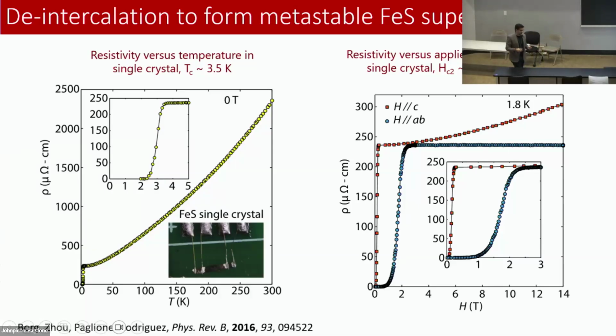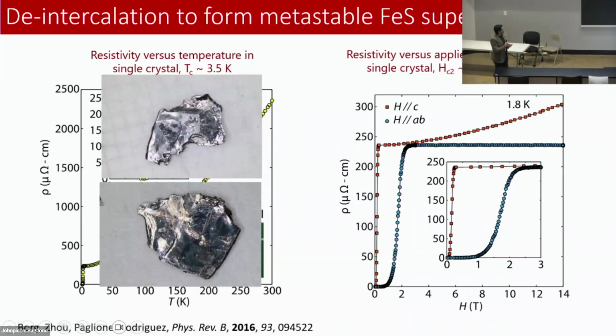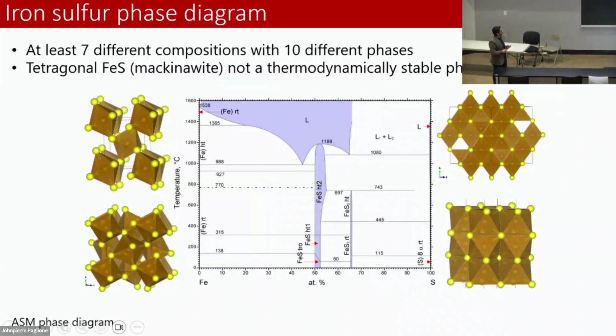Same for this compound, but you're left with that potassium. So what we've done is we grew large crystals, and then we removed the potassium, and we made pure iron sulfide crystals this way, and made a superconductor. It's not as high as iron selenide, but we thought it was really neat that we could make an iron sulfide superconductor. If you look at a phase diagram of iron and sulfur, you're not going to find that compound on that phase diagram. Okay?